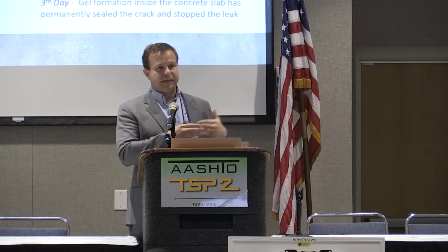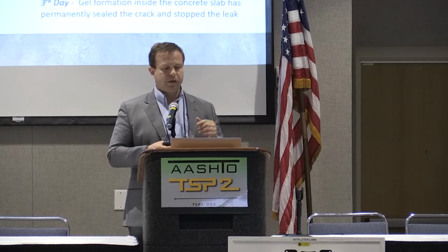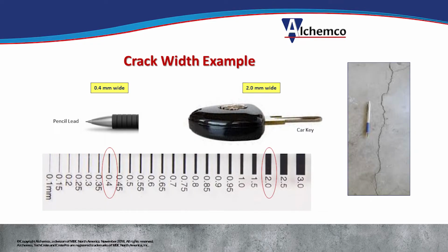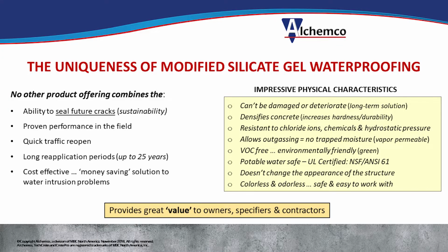And again, as we have seen, it's a spray-applied material. I'm going to show more videos. And this technology has the ability to seal a crack up to 2 millimeters, which is the width of a car key. So if you can put your car key inside that crack, this technology is going to be able to seal that crack so water will no longer penetrate. In addition to that, this material is also going to seal cracks that happen after the application, of a width of 0.4 millimeters. So here we have a few points of this technology. First of all is really the ability to seal not only existing cracks, but also cracks that happen after the application.